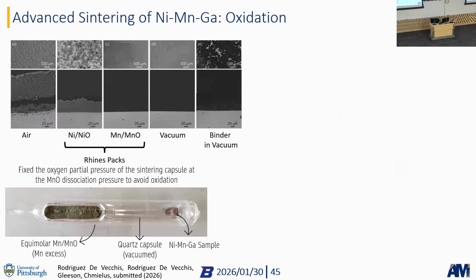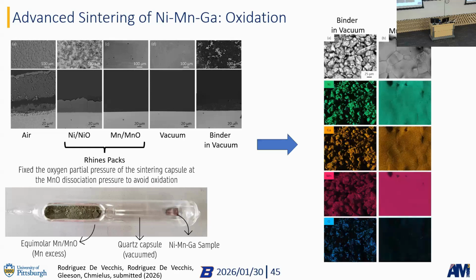She used a very classic method of a Rhines pack that creates an oxygen partial pressure in an encapsulation tube to actually eliminate oxidation completely, right? So this is a really cool result. When you look here at binder in vacuum versus binder in manganese oxide, there is no oxygen, or very, very little. So this is amazing. Now we have a mechanism that we can use to sinter nickel, manganese, gallium without any oxidation, with binder present, right? That's really cool because we eliminate contamination now.